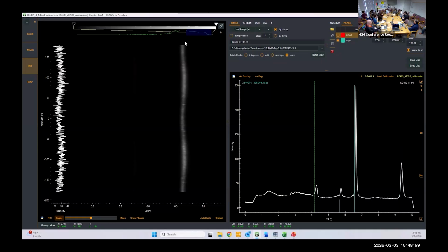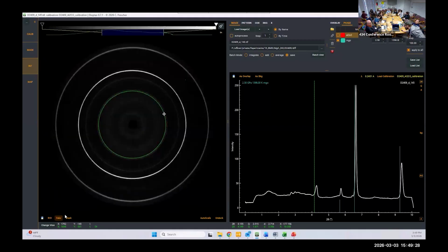So when cos squared theta equals 1/3, you'll have 1 minus 3 times 1/3. This will be 0 if you don't have any differential strain, and you'll just be left with the pressure. The angle at which that happens is, I think, around 54 degrees. So if you want to know just the pressure, you'll have to look at the d-spacing at whatever 54 degrees, somewhere around there.